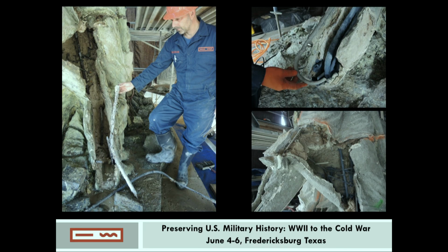Some rebar were not replaced as they were embedded in the concrete shell or were judged to be corroded to less than 50% of the bar thickness. These rebar were mechanically cleaned with steel brushes, pneumatic chisels, etc. Some were blasted with fine crushed glass and coated with 2 coats of Mapefer, which is a corrosion inhibiting mortar. That's also in the paper. And you can see that here on the top right, that purple coloured coating, that's the corrosion inhibiting mortar.